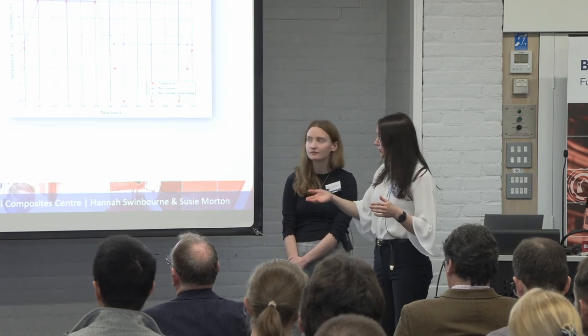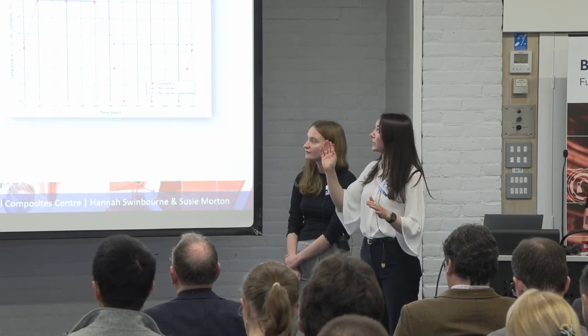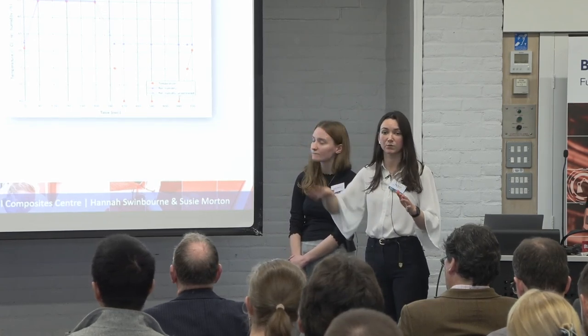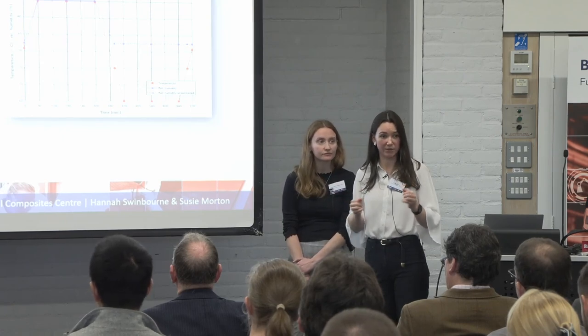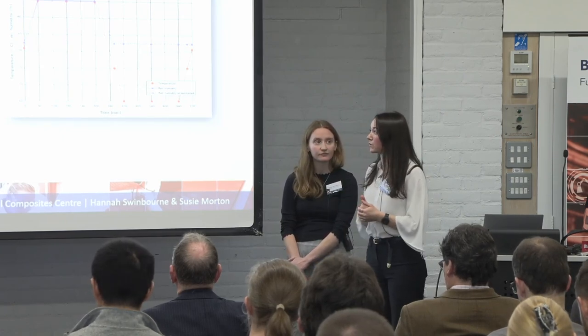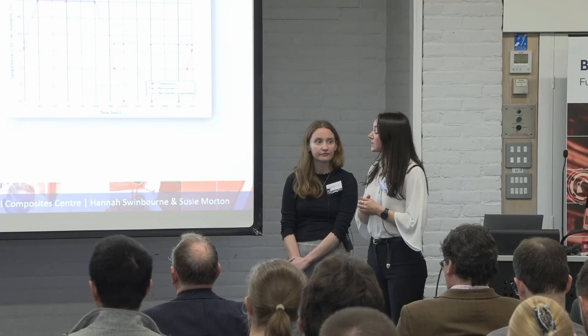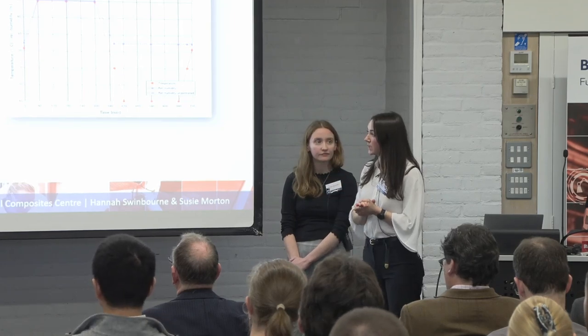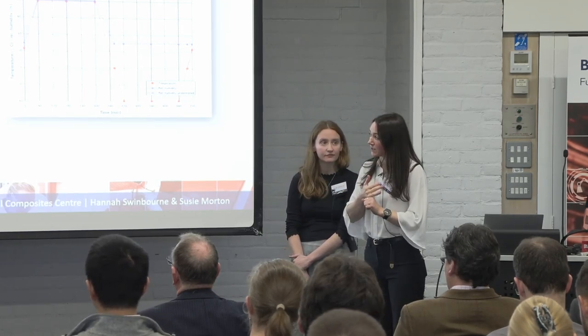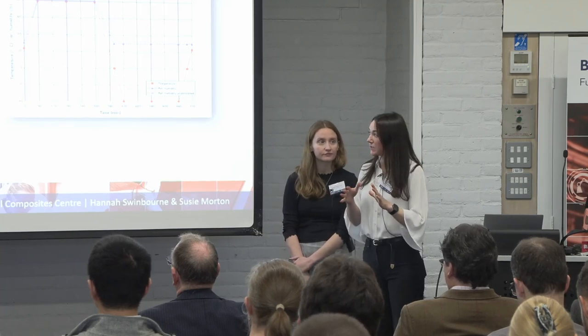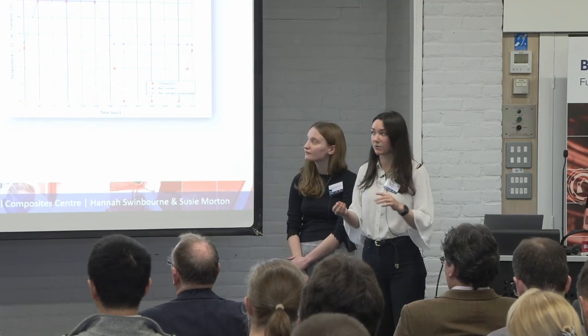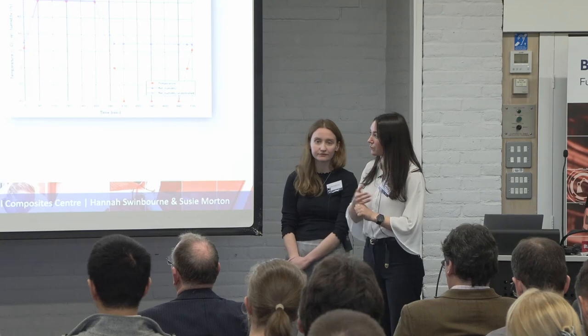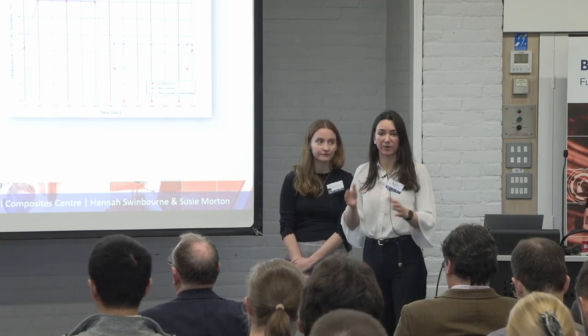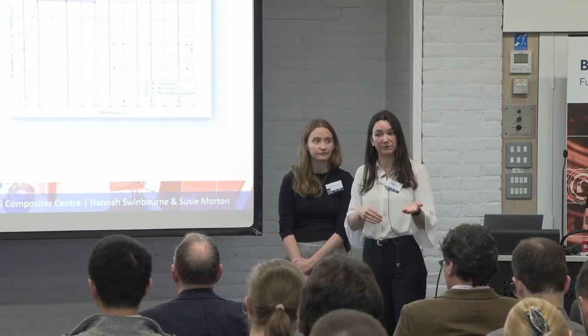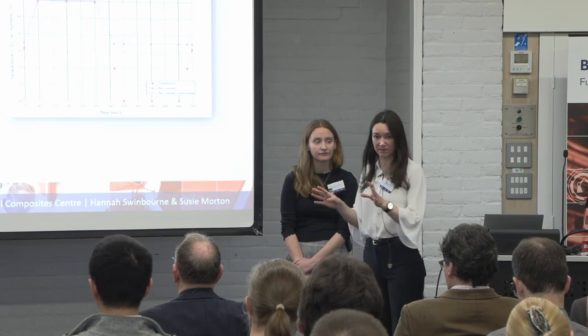So prior to processing, we put it through both a temperature and humidity cycle, which is familiar to those in industry, maybe the automotive industry. We used a Volkswagen standard called the PV1200. And we had a look at the tensile strength and the stiffness of these materials after putting it through the cycle. And we found that for tensile strength, flax reduced by about 5%, whereas the glass, interestingly, reduced by about 10%.